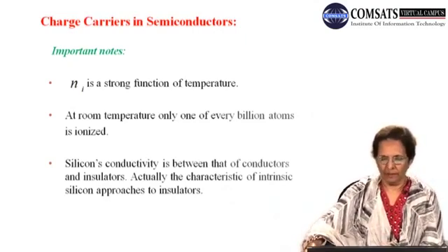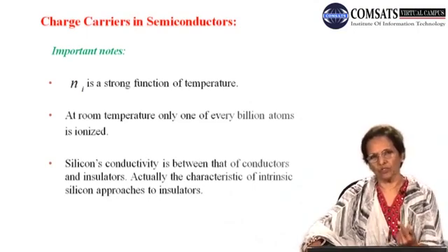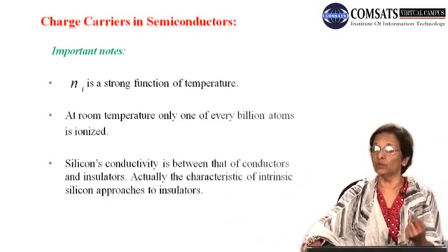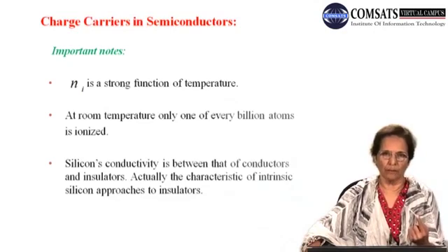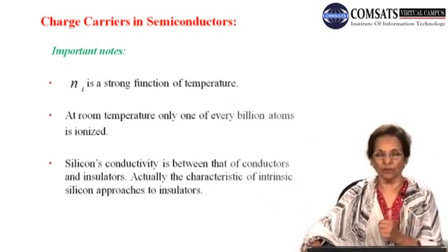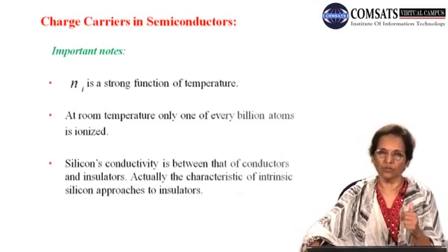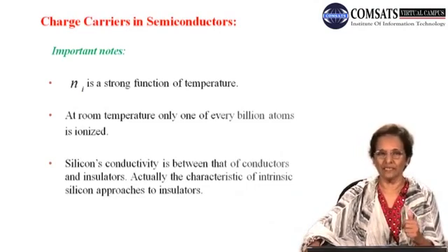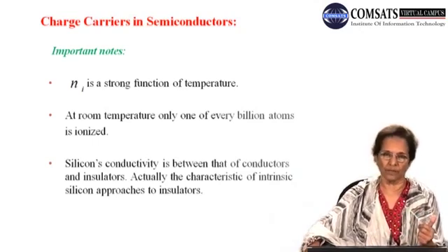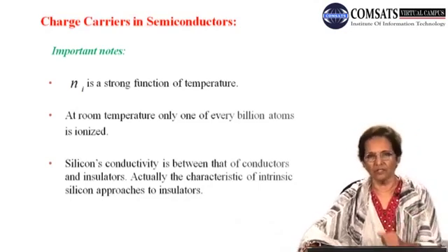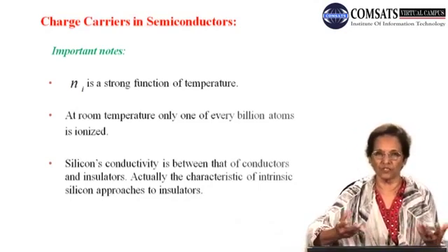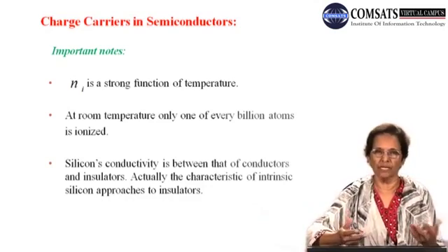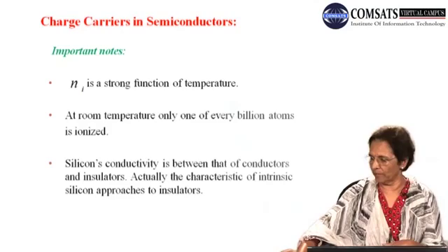And finally, this thermal generation process is a very important mechanism. It is this very process which distinguishes silicon from insulators and from metals. Because of this thermal generation process, silicon, or semiconductor materials for that matter, become better conductors rather than insulators, because thermal generation gives rise to free electrons in the conduction band and free holes in the valence band.